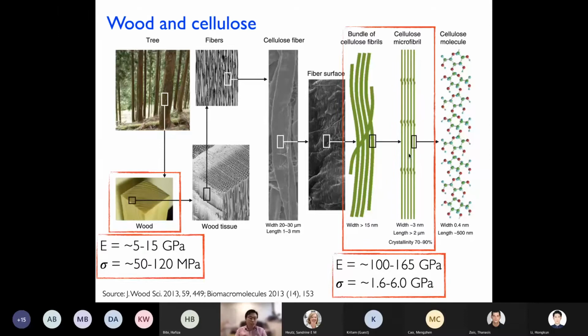The strength of these fibers was measured or estimated to be up to 6 gigapascal by researchers from the University of Kyoto about 5 years ago. So again, this value is very, very comparable to glass fibers. So the whole research in nanocellulose is actually to try and explore these high performance nanoscale fibers, even though the terminology is quite confusing, but I'll get to that in a bit. But these 3 nanometer, 15 nanometer cellulosic fibers are on the nanometer scale, as reinforcement for polymers.